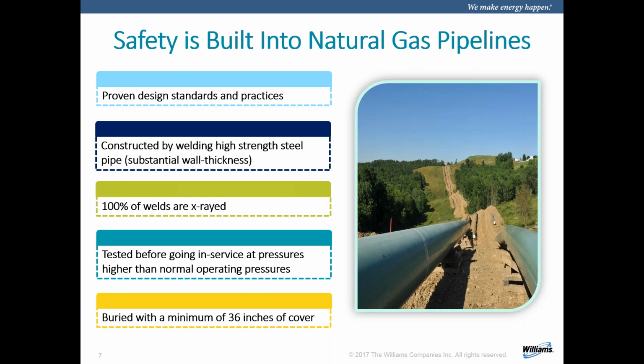Of course, a pipeline is constructed of high yield strength pipe with substantial wall thickness to ensure that the gas stays in the pipeline. We X-ray 100% of the welds when they're constructed, and before they're placed into service, the pipeline is tested at a pressure higher than normal operating pressures. So we have a sense of assurance that if there's any defect, it's going to be found through a pressure test before gas is moved through the pipeline. And then we want to have a barrier of cover on top of us, so we try to have a 36-inch cover on top of our pipeline. That's according to the regulation.